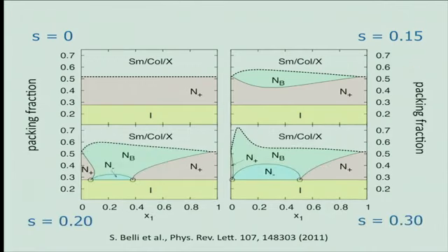Apparently this seems to be the case also for the binary mixture, independently of the size asymmetry, since you expect a very weakly first order transition at mole fraction 1 and 0, and at the same time, due to the appearance of these Landau critical points, you have also continuous transitions, and apparently that's the case also in the regimes in between. So this is our interpretation, maybe not really to motivate the absence of demixing, but to try to interpret it.